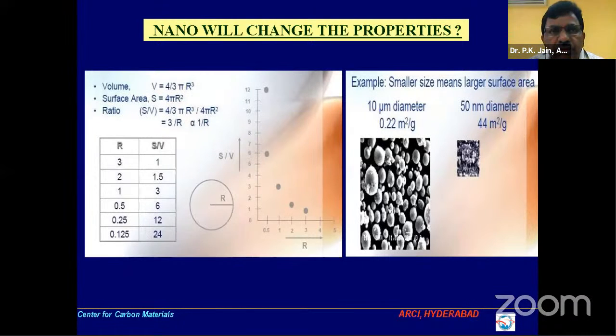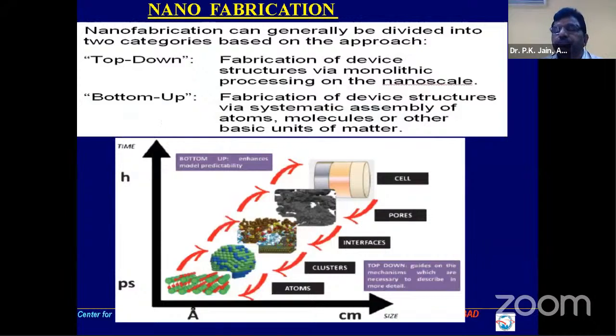So we use this very commonly in day to day life, but we don't understand what exactly is happening scientifically. A 10 micrometer powder will give you 0.22 meter square per gram surface area. But when it becomes 50 nanometer, the surface area is almost more than 200 times, which becomes 44 meter square per gram. The particle size, the surface area, the surface to volume ratio, everything can be multiplied.